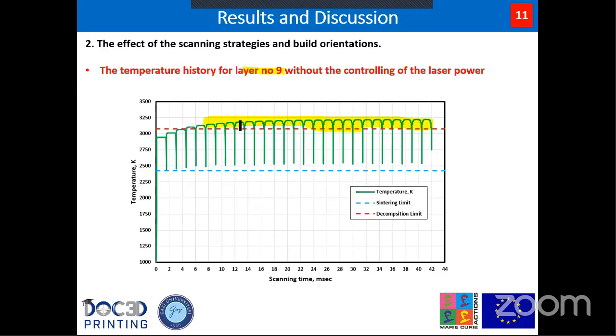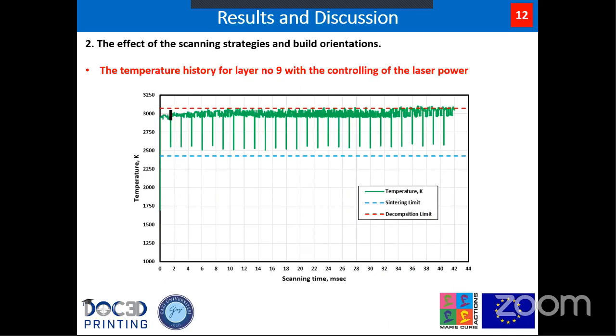So how to solve this problem? It can be solved by controlling the temperature or controlling the scanning speed. The temperature can be controlled using a controller for the power, where we can reduce the power according to the number of layers. So we updated our model and included a subroutine for a laser power controller during building. When we applied this subroutine, we can see that the scanning is below the decomposition limit for layer number 9.